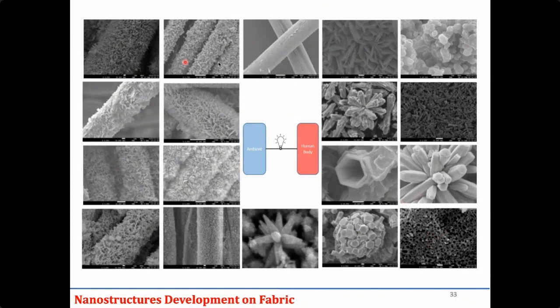So there are different nanostructures, because whenever we talk about nanostructures, as I said in the earlier example, the phonon scattering effect. If you want to decrease the phonon contribution, what we do is we decrease the phonon wavelength. So whenever we make the materials less than 300 nanometers, it can decrease the phonon phenomena. So obviously we increase the ZT.